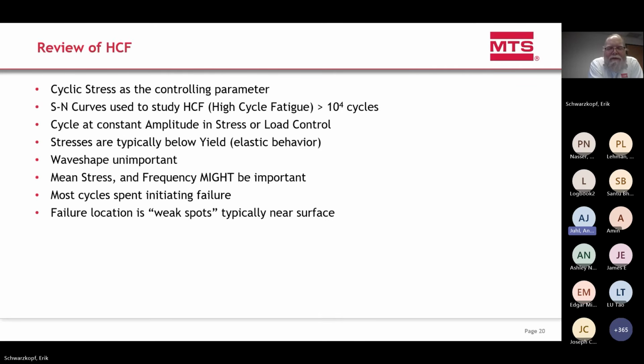Wave shape is generally not important in HCF. Mean stress and frequency might be important, depending on what other things are going on, what other environments are being used. Most of those cycles are spent initiating failure. A small fraction of the total number of cycles to failure is used to grow a crack. Most of the cycles are used to initiate or create the crack. And finally, failure location is at weak spots in the material. In the case of these axial specimens, it's typically near the surface, because that's where the stress concentrations lie.